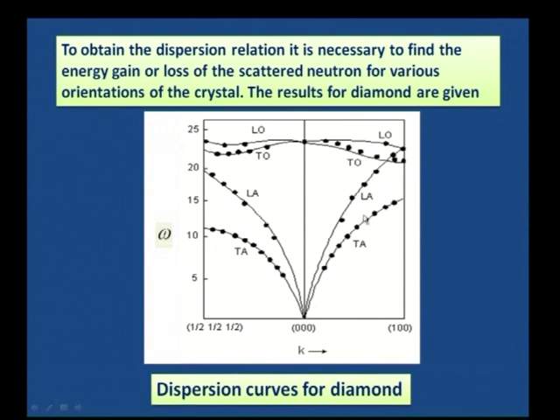This is a theoretical curve, obviously this continuous line is a theoretical curve, and the experimental points are found here. These were diamond. TA refers to transverse acoustical, LA refers to longitudinal acoustical. I mentioned transverse and longitudinal. TO is the transverse optical mode, LO is the longitudinal optical. Therefore, as we had in the diatomic case, you have the acoustical branch and then the optical branch. Now you have both the transverse and longitudinal modes. The continuous line is the theoretical line that you have to formulate, as we did in the one-dimensional case, monatomic and diatomic. The force constants have to be taken into account, and you have to form a dynamical matrix connecting omega and k.